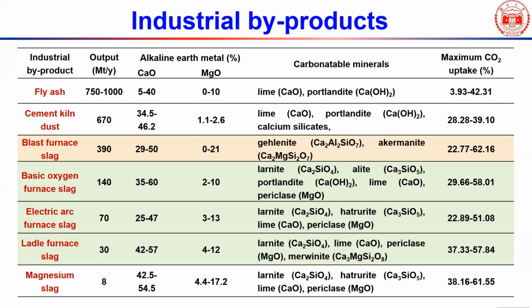Fly ash, cement kiln dust, and blast furnace slag. Some of them also give the maximum CO2 uptake. Okay. Here, I want to point out this maximum is a very theoretical value. And actually, the calcium oxide in glass material is not so easy to be carbonated. The window glass contains about 10% lime and 13% sodium oxide. So as I said, even after 100 years, you can see the glass never gets carbonated, or the carbonated layer could be very, very thin.